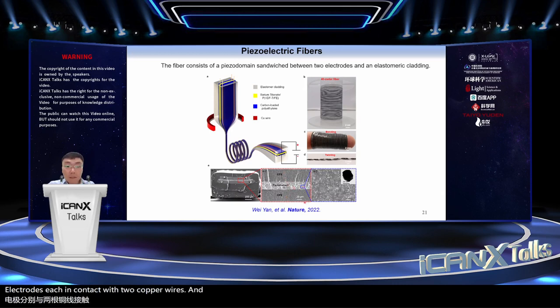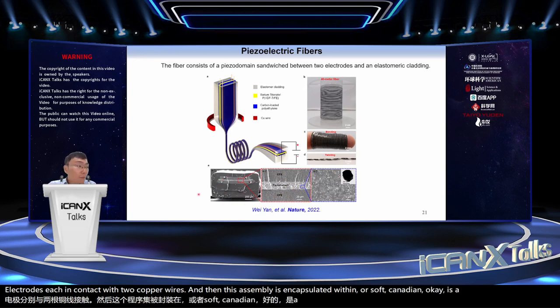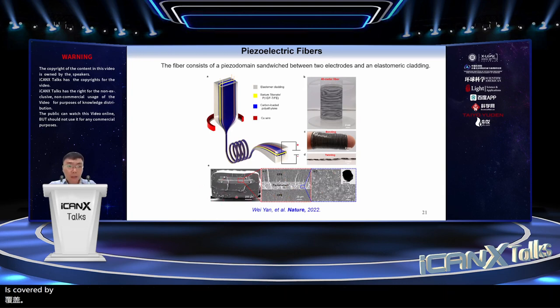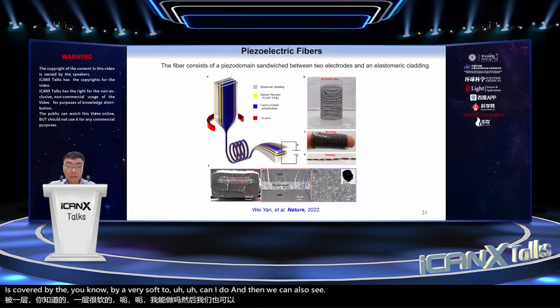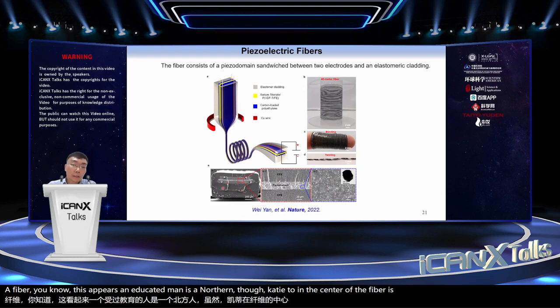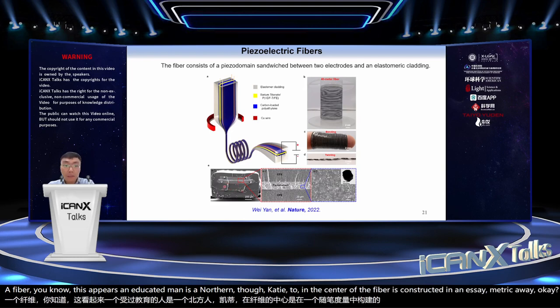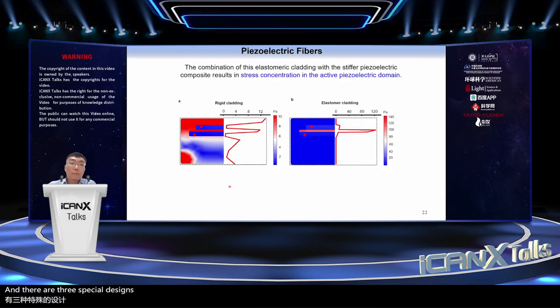And then this assembly is encapsulated within a very soft cladding. We can also see that this piezoelectric domain is not located in the center of the fiber; it is constructed in an asymmetric way. So there are three special designs for this fiber.